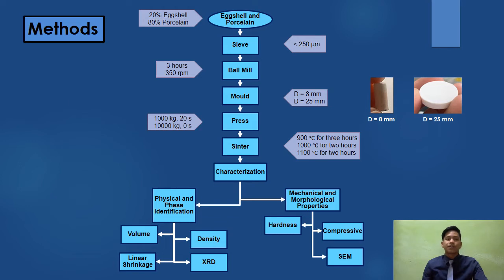The compressive test was applied to identify their strength and elastic modulus with a set crosshead speed of 1 mm per minute. The SEM images were taken to identify the morphological properties of the samples. The number of samples for physical and mechanical properties evaluation will be 3.